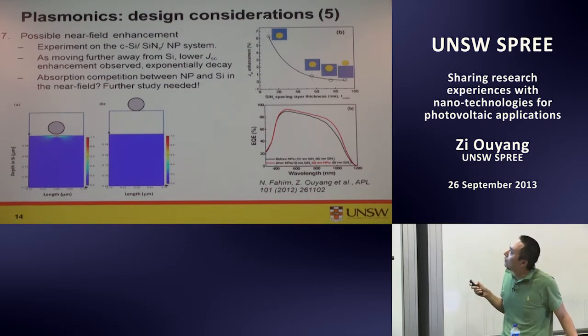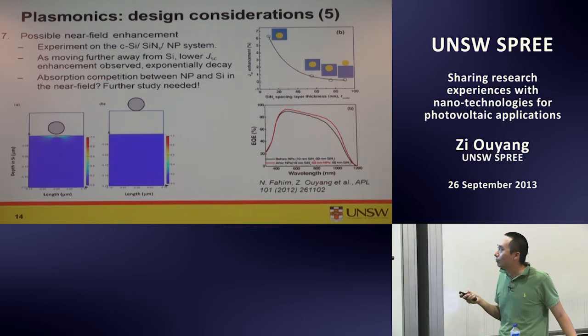So we did a series of experiments, putting the nanoparticles embedded at different positions in the silicon nitride. And what we find is that as we move further away from silicon, we get lower JSC enhancement. And this curve is fitted with an exponential function. And we know the near field decay is an exponential function. So this is a sort of indirect proof of the near field enhancement. But obviously further study is needed, because in the near field, the silicon has to compete with the nanoparticle in terms of absorption. The parasitic absorption of the nanoparticle is very strong, and silicon, because it's an indirect bandgap material, you think it might not be very good. So more details of the competition need to be studied before we have a solid conclusion.